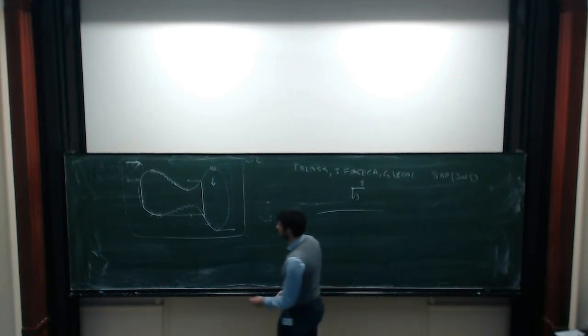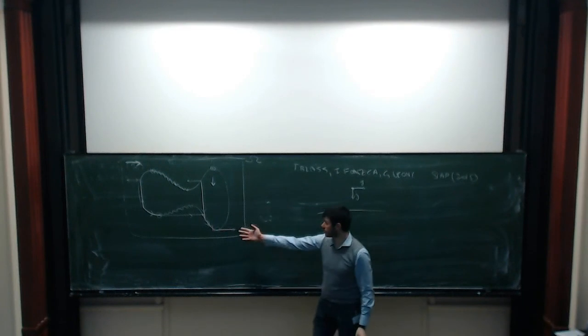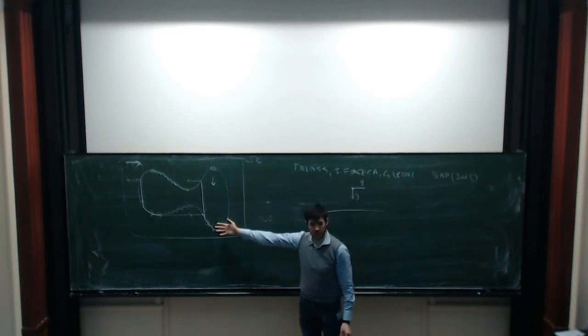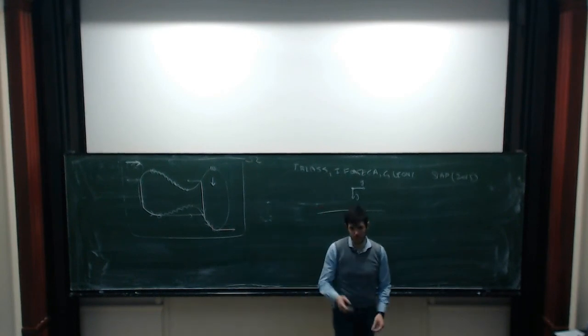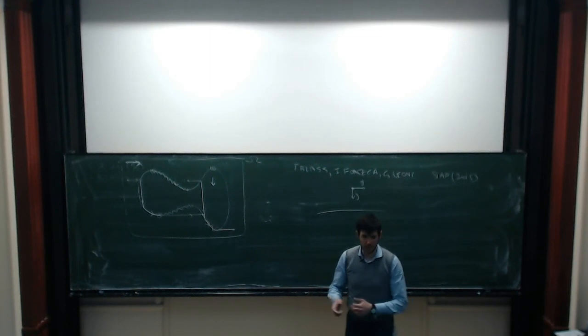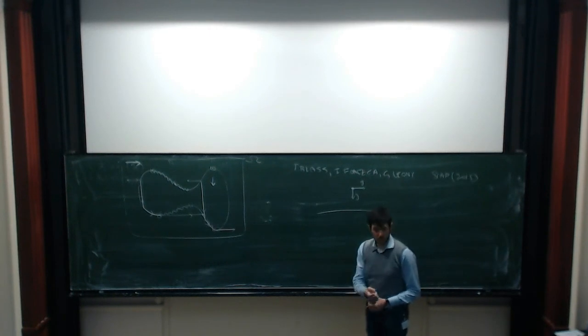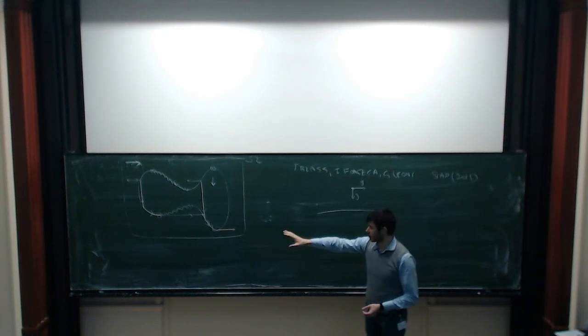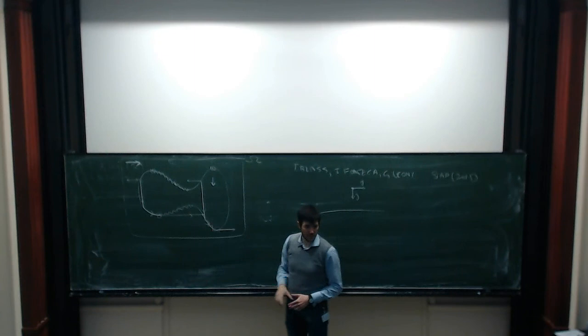In numerical simulations with 12 dislocations in a disk with random initial conditions, one observes either straight lines, curly lines, or direction switches. Computing the ambiguity set A numerically amounts to fixing all but one dislocation and finding points where two glide directions simultaneously maximize the scalar product with the force. Discretizing time and always picking the maximizing direction produces zigzagging, which can be seen as a faster time scale approximation to fine cross-slip.